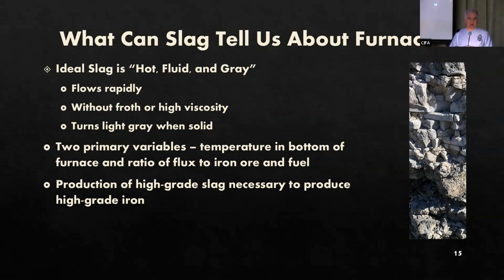In the 18th and 19th century, without detailed chemical or physical ways to measure these things, the furnace workers had to rely on what they could physically observe in terms of the characteristics of the iron and the slag. And that gave rise to two primary variables that the furnace workers tried to control in operating the furnace. First, the temperature at the bottom of the furnace when the air was blown in and the slag and the liquid iron accumulated. And secondly, the proportion of limestone or the flux that was added in comparison to the iron ore and the fuel that was added into the furnace.